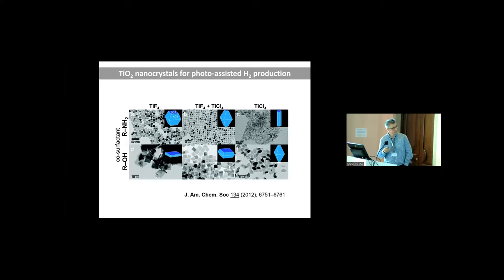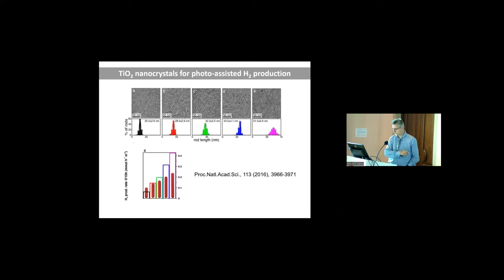The first talk this morning was fantastic, and I do not need to spend more time emphasizing that. And I'll mention that I'll focus on this brookite type TiO2 for hydrogen production. By playing with the synthesis and modulating the length of the nanorods of brookite, keeping constant the thickness and putting standard platinum co-catalyst with the same well-defined nanotechnological approach, we were able to demonstrate that the amount of hydrogen you're producing depends on the length of the nanorods.